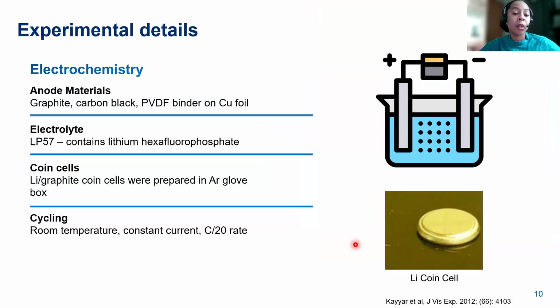And by aging, I mean cycling the battery multiple times. So these are some of the electrochemical details that were done. The electrochemistry was done by collaborator Teresa and Sinna at the University of Cambridge. So we have our anode materials, which consist of graphite, carbon black, a PVDF binder on copper foil. We use the electrolyte that contains lithium hexafluorophosphate, and she prepared a lithium graphite coin cell as pictured here. This is what it looks like, and this was all prepared in an argon glove box because lithium is very air and moisture sensitive. That will become important later. And then she cycled them at room temperature, constant current, and a C/20 rate, which means it was charged and discharged for 20 hours each. So this is a pretty slow cycling process.